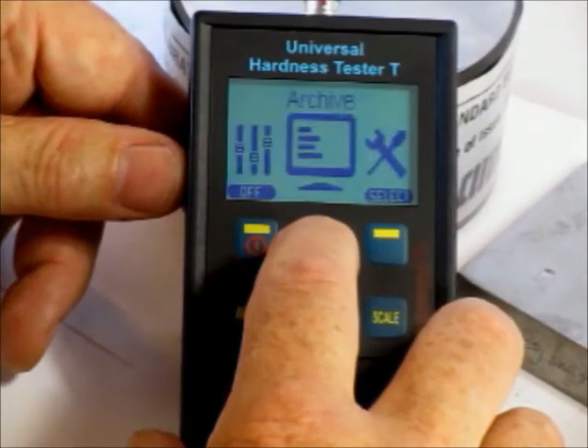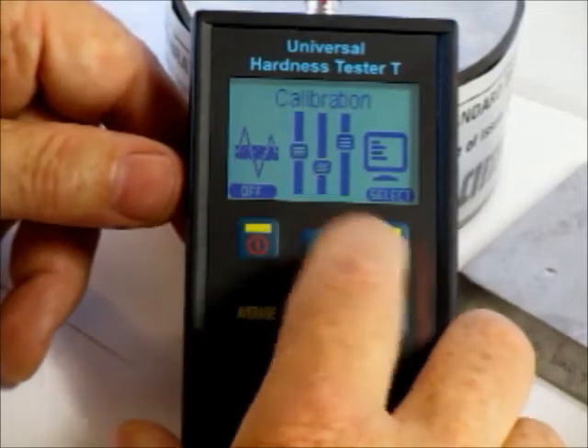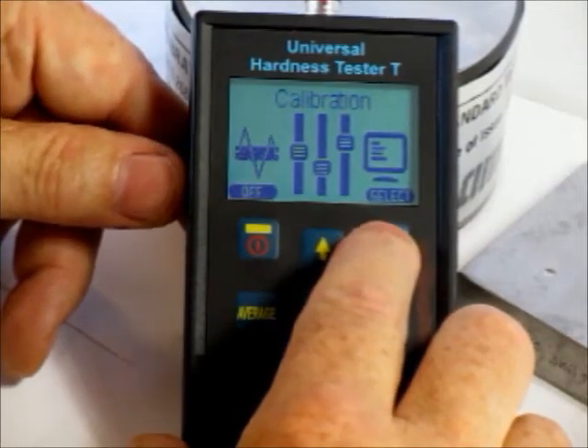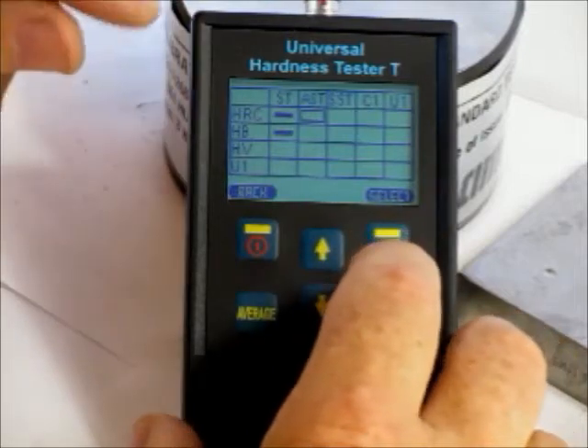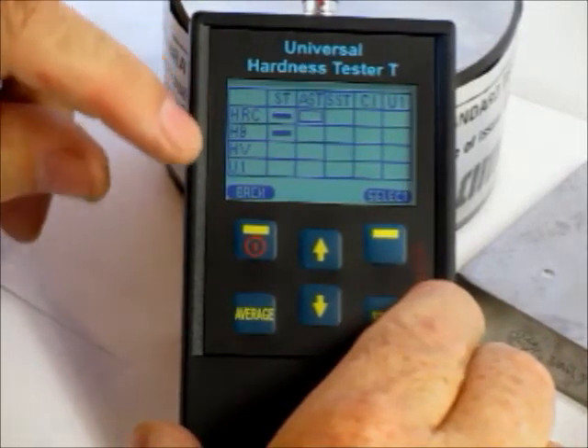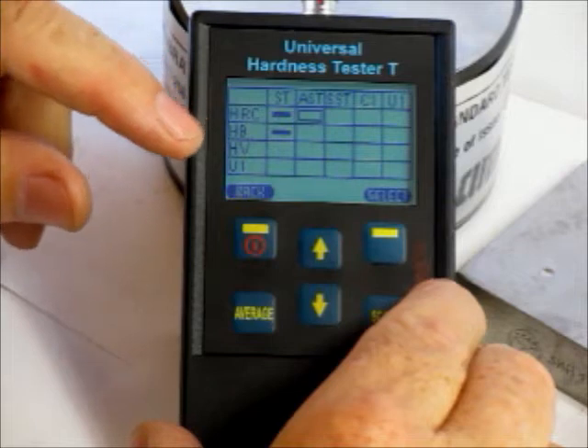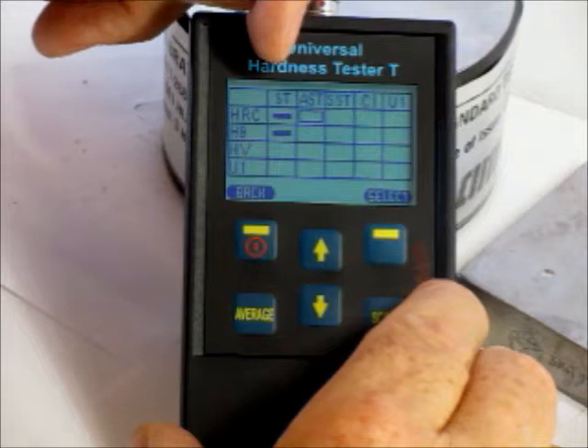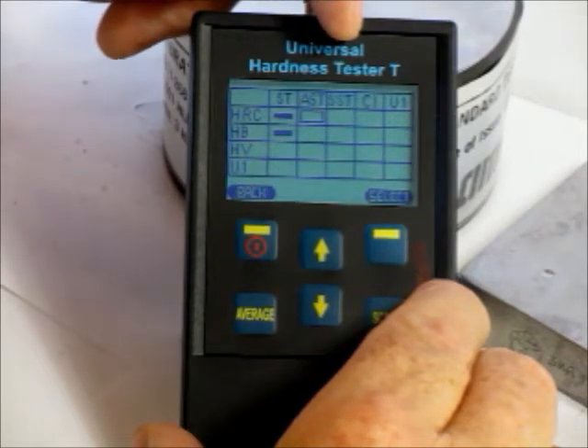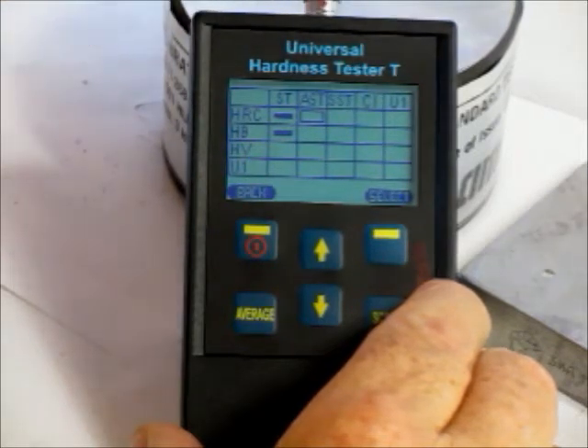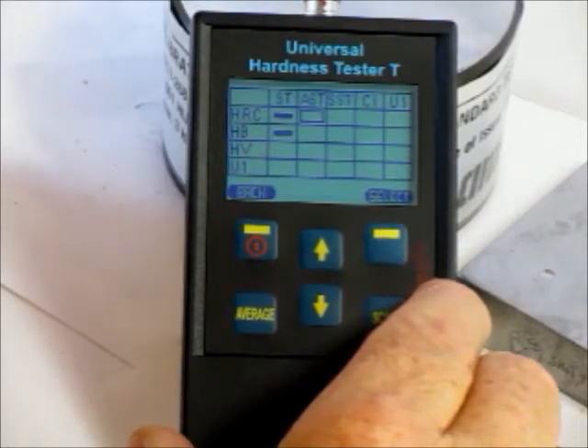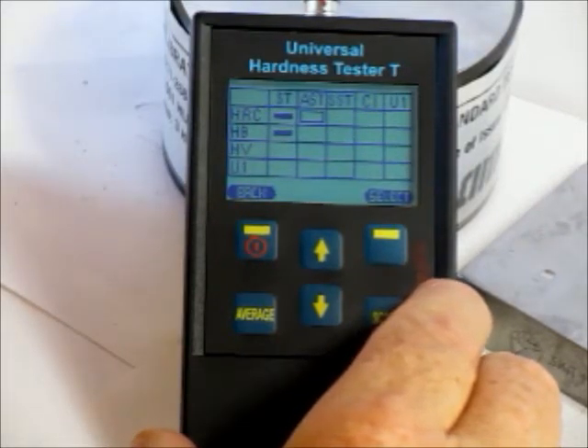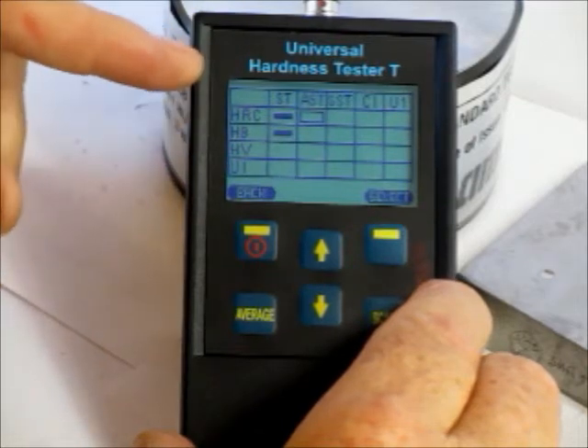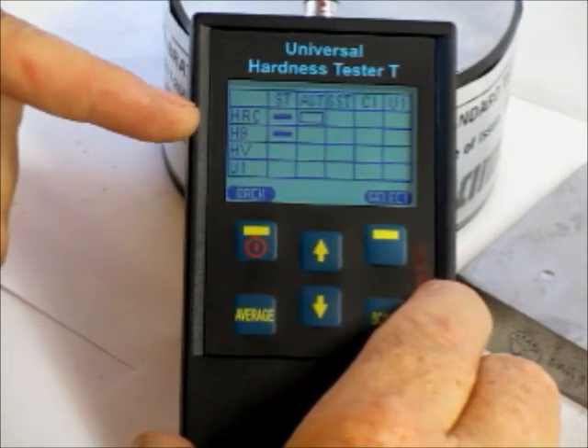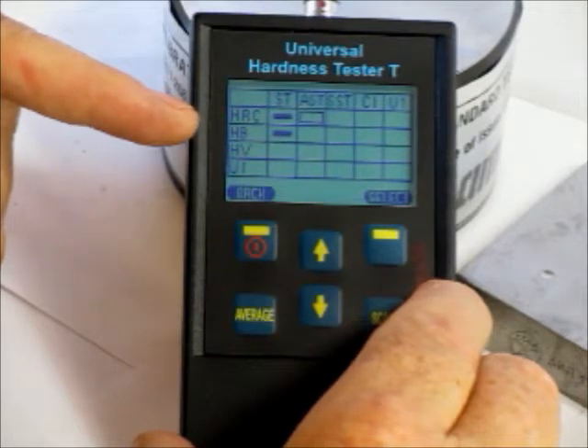So if I scroll back to calibration, we're on the calibration display, hit the select button, and you can see here we have the scale, so hardness and Rockwell C, Brinell, Vickers, and we have even a user defined. We can store this as just steel, or AST as alloy steel, stainless steel, and then 2 user defined ones. So you could do, say, titanium or some exotic material if you wish to. We do pre-calibrate the units for Rockwell C and Brinell for just low carbon steel or mild steels.